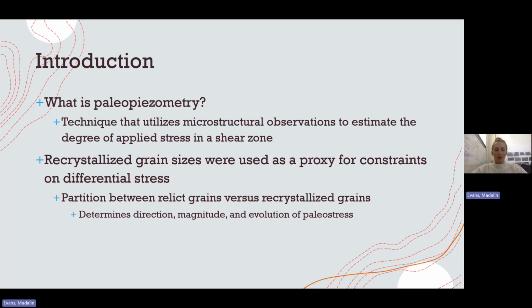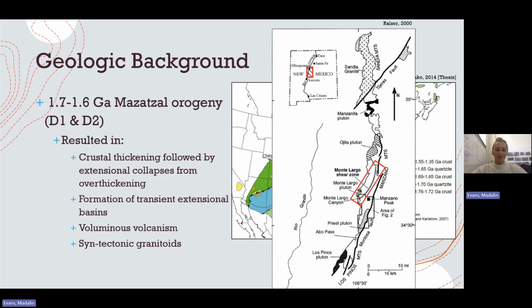So what is paleopiezometry? It is a technique that utilizes microstructural observations to estimate the degree of applied stress in a shear zone. This provides insight into the magnitude of stress that may have operated during shear zone formation. Recrystallized grain sizes were used as a proxy for constraints on differential stress. Other paleopiezometric techniques may be administered on a sample based on the objectives of research as well as the limitations of that sample. But in this case, we are just focusing on the recrystallized grain sizes, in which we had to partition between the relic grains versus recrystallized grains. This helps determine the direction, magnitude, and evolution of paleostress.